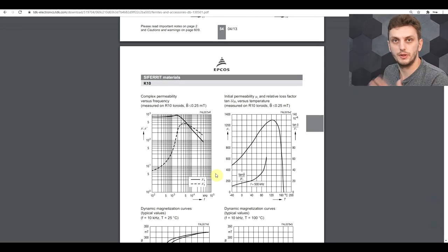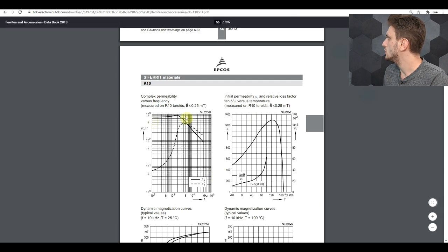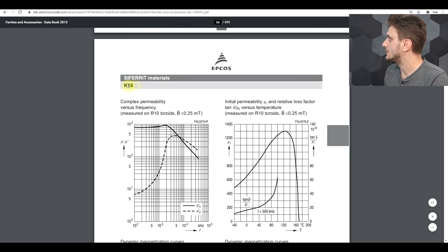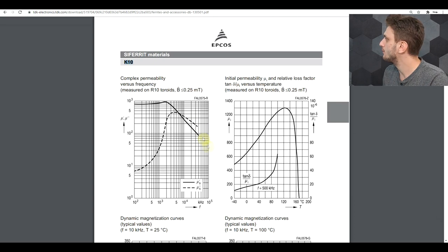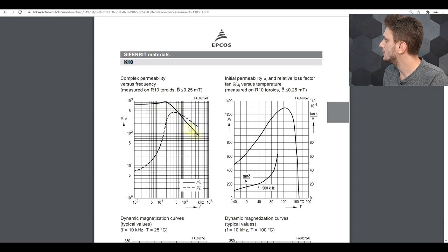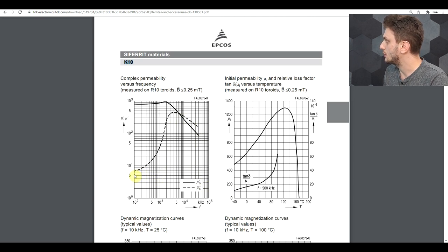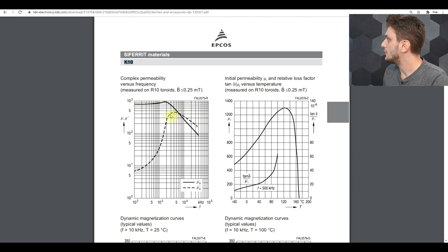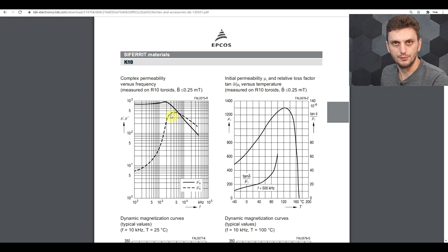Now the problem of real and imaginary permeability is not something that is restricted to iron core. If we look at a good ferrite material data sheet, we will see the exact same curves. So what I have here is an example from a TDK-EPCOS data sheet. Here they're analyzing the K10 material, but all of the materials will have these properties. Basically what they're showing us here is how your real permeability, the solid line, and the imaginary permeability vary with frequency. So with this material, if you use it at low frequencies it's predominantly inductive, but at higher frequencies it will become predominantly resistive and lossy. So what's the difference between ferrite-based power components and ferrite-based filter components? Well, not much really. It all depends on the frequency at which you use them, and the way in which the composition of the ferrite is fine-tuned to enhance either the inductive behavior or the resistive behavior. For a power component you will most likely want the inductive behavior to have minimal losses, whereas for the filter component you'll most likely want the resistive behavior, because that way you will eliminate any sort of noise directly out of the circuit. You will not have to handle it like with an inductor.